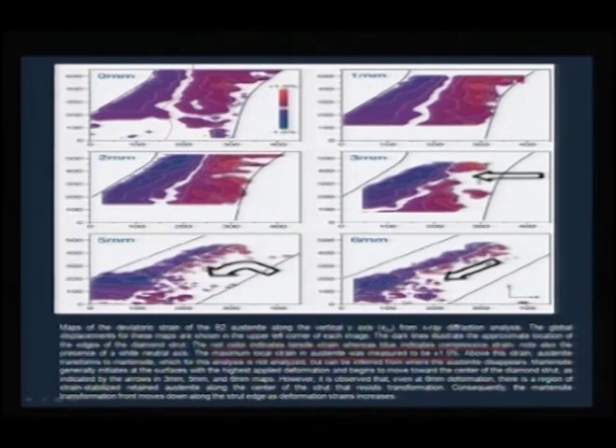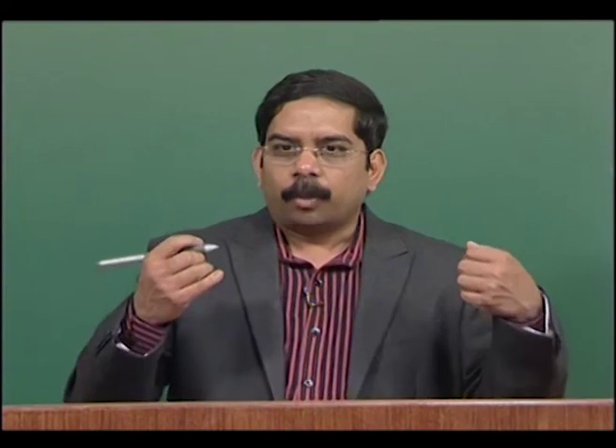Now, if you start deploying the stent, you can see how the transformation occurs. At 1 millimeter you do not see much change, but when you go to 2 millimeters, then 3, 5 and 6 millimeters, you can clearly see the change between the compressive strain and the tensile strain. Especially when you deploy the stent beyond 3 millimeters and go all the way up to 6 millimeters, you can see there is a complete transformation of austenite to martensite. So, we can clearly map what sort of phase transformation is occurring when you apply pressure inside your cardiovascular system. This is a useful way to understand how much loading the stent can take, how far you can deploy it, and what the risk factor involved is.